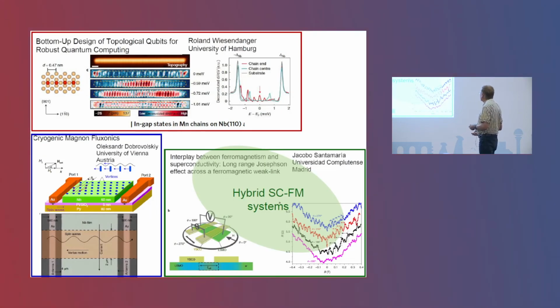Last but not least, of course, this is a hybrid superconducting ferromagnetic system. In this case, in my opinion, the magnets play a secondary role, because most of the focus is to find the most interesting, spectacular phenomena in the superconductor, like, for instance, topological superconductivity, the emergence of Majorana fermions and Majorana modes, but also a feedback from a superconductor to the magnet was actually very interesting. That was nicely demonstrated by the plenary talk of Roland Wiesendanger from the University of Hamburg, where they built up a spin chain of manganese atom by atom on the surface of superconducting niobium, and studied the electronic structure of this chain.